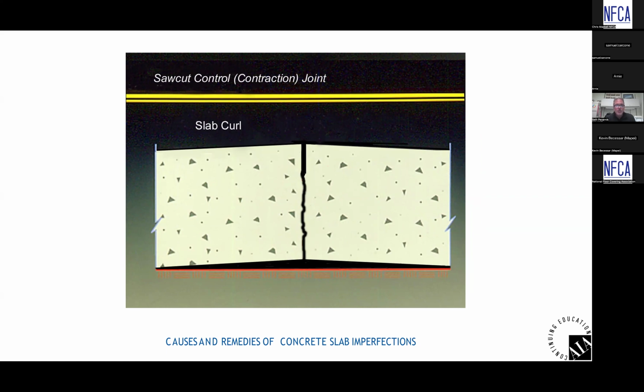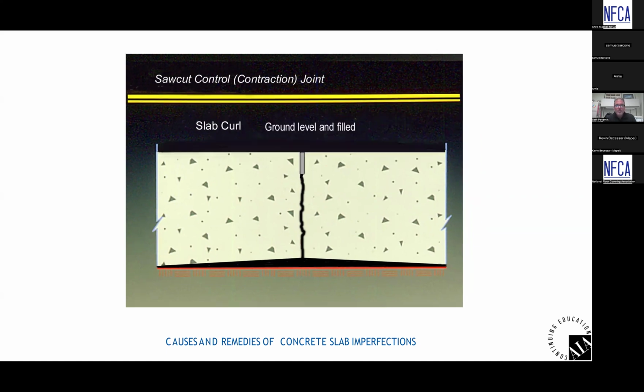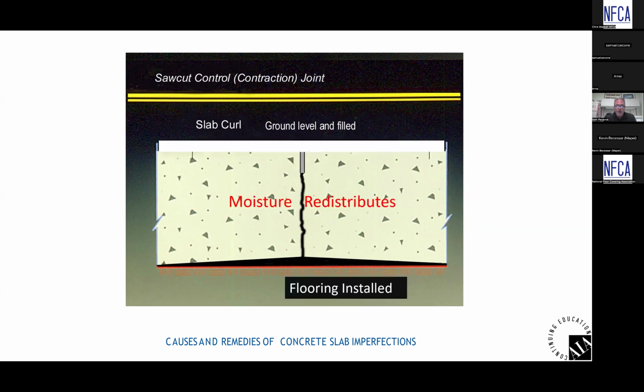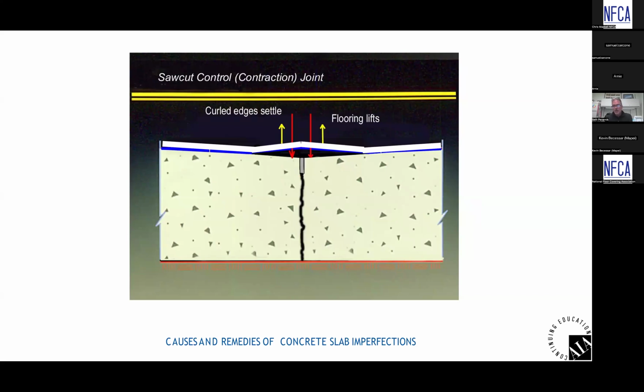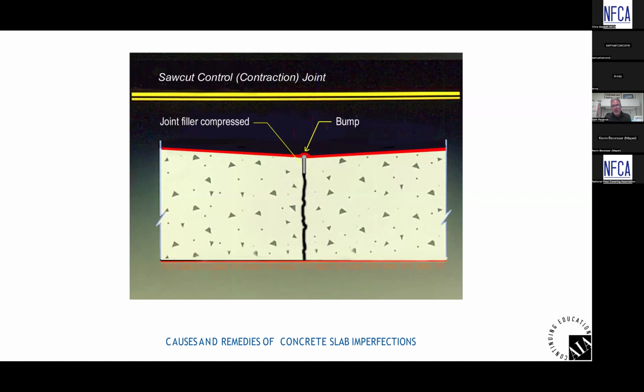So what's the natural thing to do for any floor covering installer? He'll come in and grind that curled slab so that it's flat, then fill the joint with a patching material, and then the floor covering is installed. Everything looks great aesthetically. But what can really happen is the moisture redistributes within the concrete, and when it does so, the two concrete slabs relax, and worst case scenario, as that joint at the top that's been filled gets closer together, it can cause failure of the flooring, basically disbonding right at the joint. Bare minimum, what might happen is you extrude the patching material out of the joint, and it creates a bump through the finished flooring. So it looks like a mole run in your finished flooring.